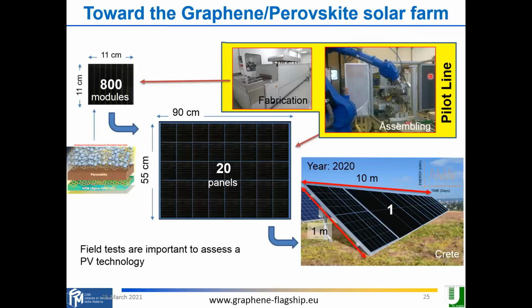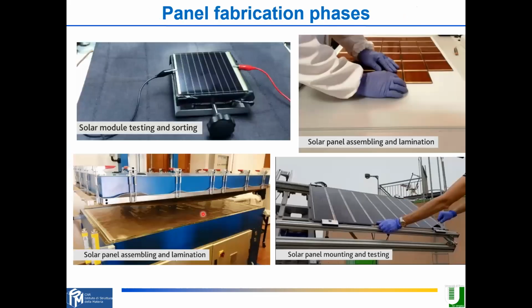Of course, I mean, module is not enough. And as we know from Japan rules for putting an object in the market, we need to do a field test. So field test is becoming very important for perovskite technology. And this is our plan, we did actually, to realize panels and then to create a field test and to do this in a semi-automated method. So we were able to realize not 800, but 400 modules, almost half of them, and half we still need to prepare. And these were the small modules.